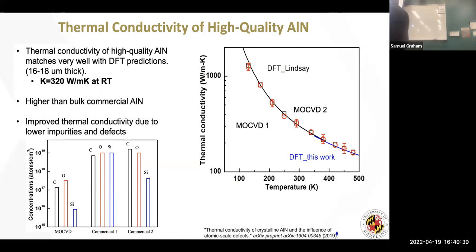So this is the chemical analysis, this image right here, the chemical analysis of impurities of commercial aluminum nitride substrates. So that's carbon, oxygen, and silicon. And so when we grew these by MOCVD, we started seeing an order of magnitude drop, or actually 2 orders of magnitude drop in some cases of these impurities. And sometimes they were hitting the detection limits of the system.